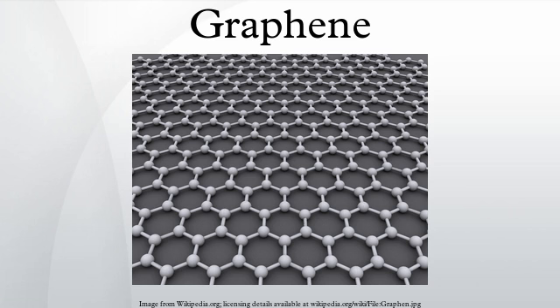Solvent-aided, dispersing graphite in a proper liquid medium can produce graphene by sonication. Graphene is separated from graphite by centrifugation, producing graphene concentrations initially up to 0.01 mg per milliliter in N-methylpyrrolidone and later to 2.1 mg per milliliter in NMP. Using a suitable ionic liquid as the dispersing liquid medium produced concentrations of 5.33 mg per milliliter. Graphene concentration produced by this method is very low, because nothing prevents the sheets from restacking due to van der Waals forces.